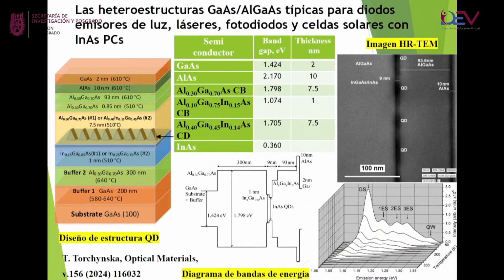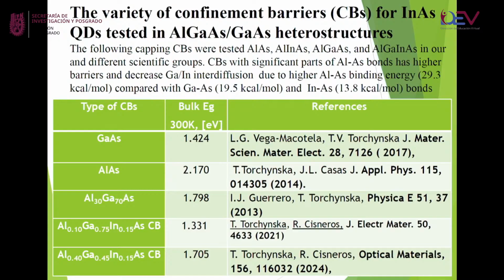Here is the laser structure that we investigated in 2005 to 2010. You could see that this structure is essentially more complicated in comparison with the first structure we had. This complicated structure includes a way to increase the intensity of luminescence by using a very high confinement barrier. I show you our publication connected with different confinement barriers. We investigated alloys of aluminium gallium arsenide, aluminium gallium indium arsenide, with different concentrations of aluminium.